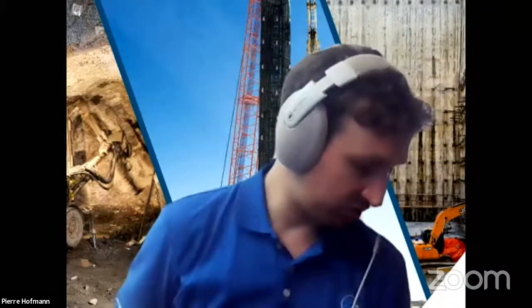It's happening. We work very closely with some major players in the industry. We have done it. We were successful in having a bar that we can heat up locally, and we have developed the machine to bend it. The main issue we have now is the strength retention in the bend section. It was much less than what I mentioned now, so we have to work on improving that. It was also durability. At this stage, with the early-stage tests with thermoplastic, we couldn't get as much performance as we would get with thermoset resin. So we are working very, very actively on this.